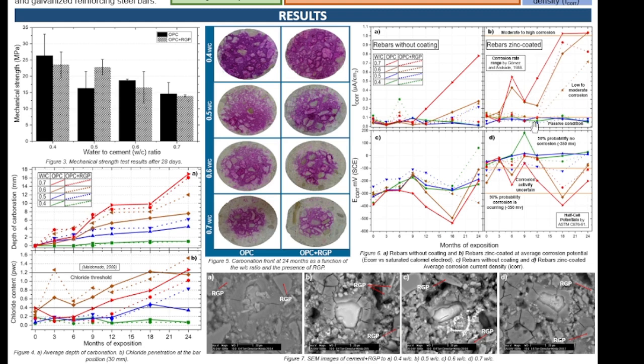On the other hand, figure 6 shows 4 graphs. Parts A and B indicate the performance of the corrosion current density, with range limits first mentioned by Gómez and Andrade in 1988, comparing reinforcing steel rebars with and without coating. In parts C and D, the graph shows the performance of the corrosion potentials, with limits mentioned by the ASTM C876-91 standard, comparing reinforcing steel rebars, zinc coated and without coating, and taking into account the comparisons of the physical protection offered by 4 water cement ratios.